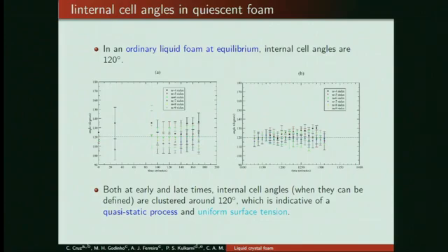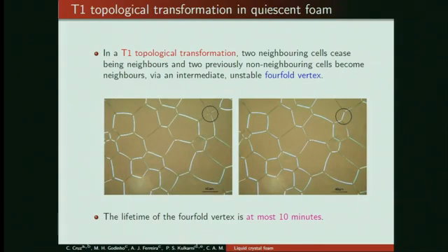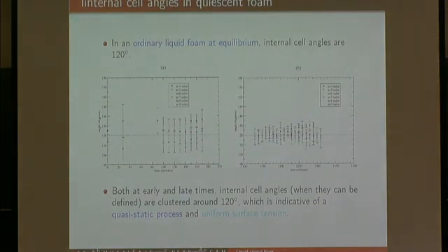One of them is that in a dry foam, that is one with small plateau borders, like what you see here, where your plateau borders are basically points, you have only threefold vertices, or your n-fold vertices for n greater than 3 are very short-lived, and the angles between films meeting at a vertex should be 120 degrees. This follows just from balancing surface tensions.